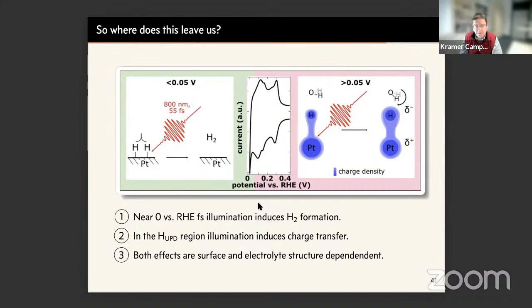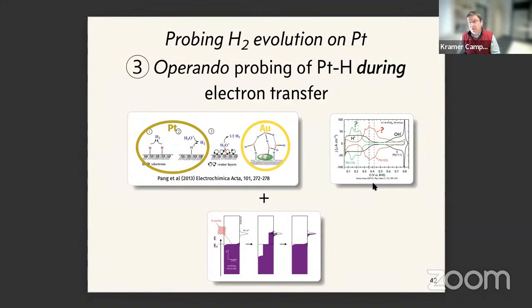So here I just sort of summarize what I have said before. So we think we can induce 2 effects. One is H2 formation, presumably by this DIMET mechanism, for reasons we can discuss. The other is charge transfer into an antibonding orbital. Both of these effects are clearly surface and electrolyte structure dependent. Okay, so this is great. The time will just work out.